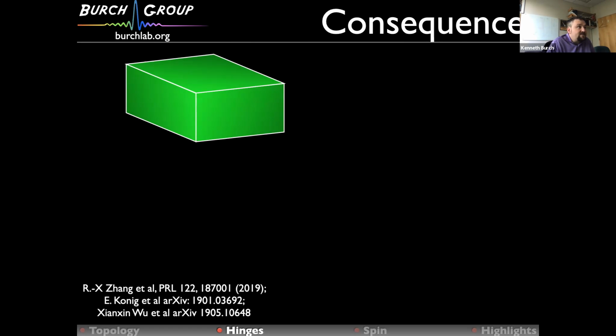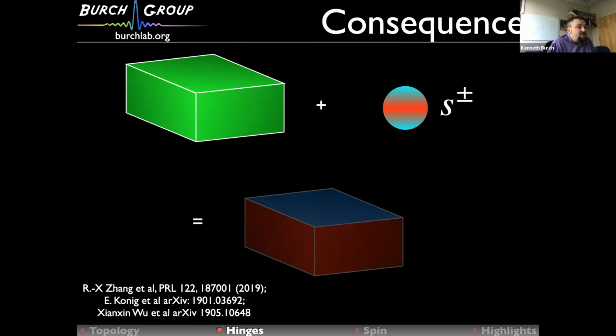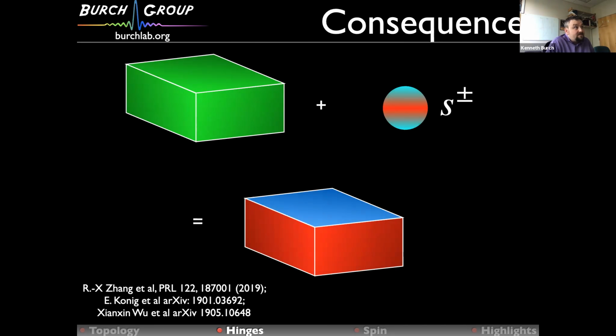Anyway, so they said, look, let's say I have these TI surface states, and I have this S plus minus order, right, where the sign of the order parameter changes from gamma to m. That means that, for example, the surface states on the top surface would pick up one sign of the order parameter. And for the states on the side surfaces, they'd be projected out to m, and so they would get a different sign of the order parameter, right? So I would literally have this sign change in the gap of my surface states, just like the construction I showed you earlier for a higher order system. And so they suggested that I should have a higher order topological superconductor with these one-dimensional hinge modes.